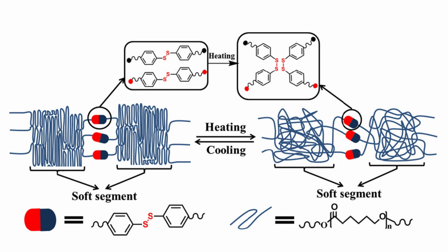The healing efficiency of thermally initiated materials is generally high, but there are some drawbacks, such as the effect of too high a healing temperature on the material's own structure, the tendency to age the material, and the inability to precisely locate the breakage.